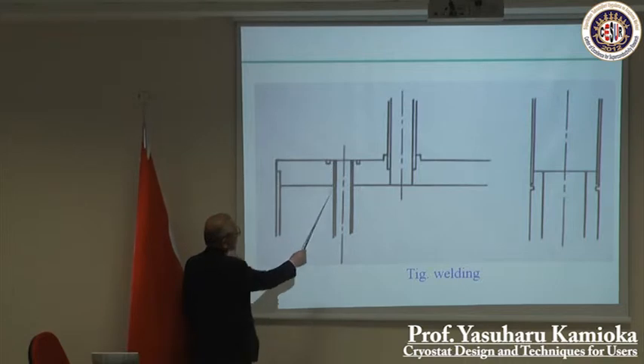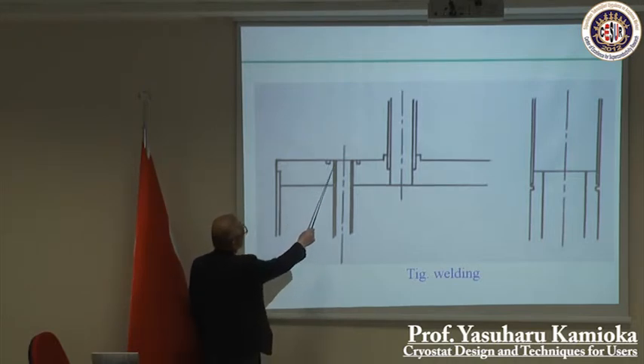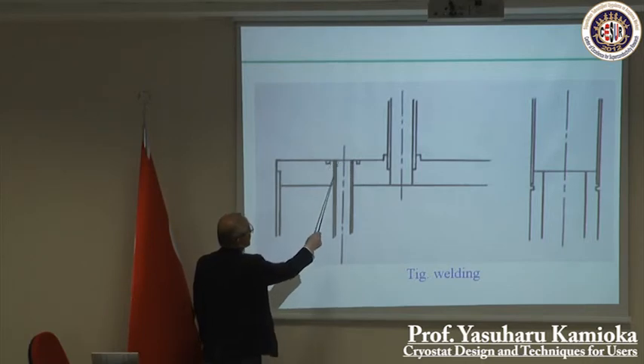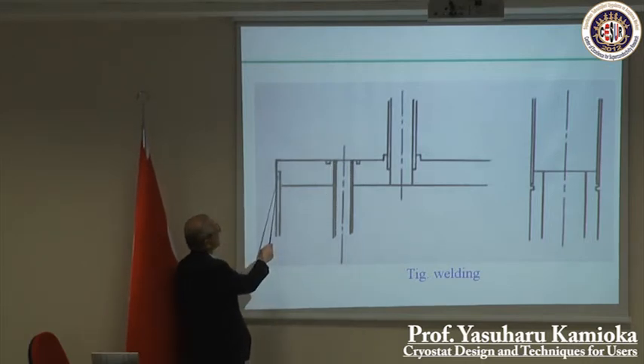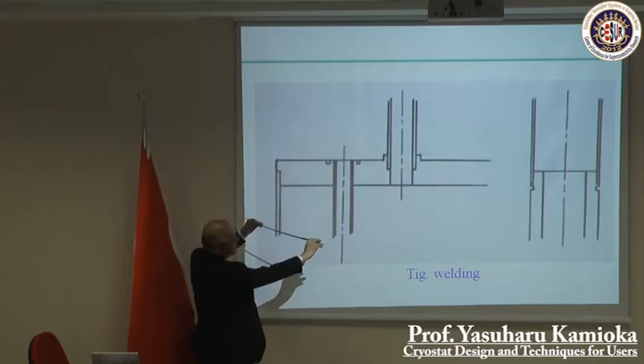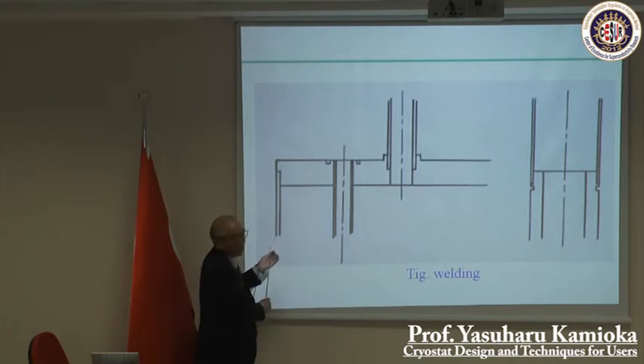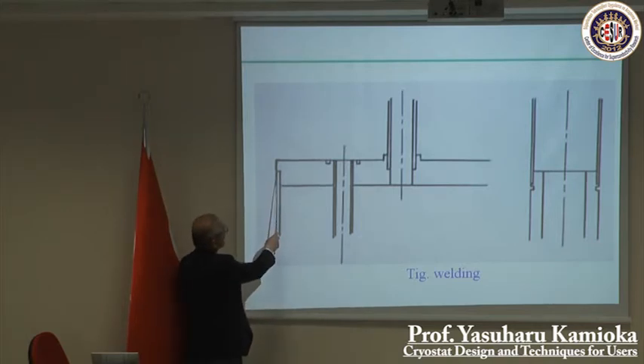And this tube is thin, but this flange is very thick. So you have to have almost the same thickness, so make a groove here, like this. Then weld here. When you weld the tube on the outside, maybe if you weld here, then the flange will bend. So in the middle, when you have a welding in the middle, then this flange cannot bend.